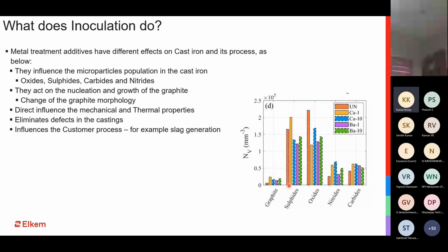So what does the inoculant basically do? You have about 3.5% of carbon. About 2% of that carbon goes into solution, as the solid solubility of carbon in iron, and then the balance 1.5% or 1.2% of whatever carbon is left has to precipitate out as graphite. That is what we want as a foundry. And if we do not make it precipitate as graphite, it would combine to form iron carbide. So what do we want to do? We want to introduce nucleating sites, favorable conditions where this carbon would precipitate out in the form of graphite.